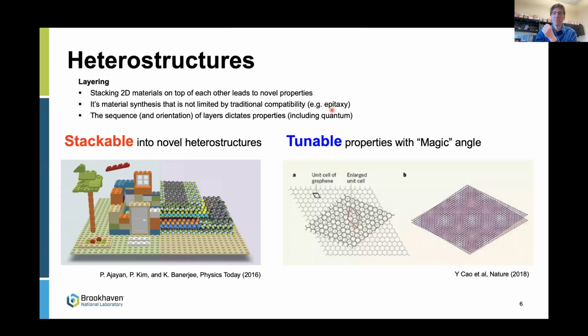And in particular, there's this concept called epitaxy, where the layer that forms on top is going to want to register itself epitaxially with the layer below. And so if you're trying to put two materials on top of each other that have really different lattice constants, like really different spacings between the atoms, it's going to be hard to do, and it might lead to a complete mess. And it might only work well if the two materials you've chosen have well-matched unit cells, crystallographic unit cells. So that's a limitation of conventional methods.